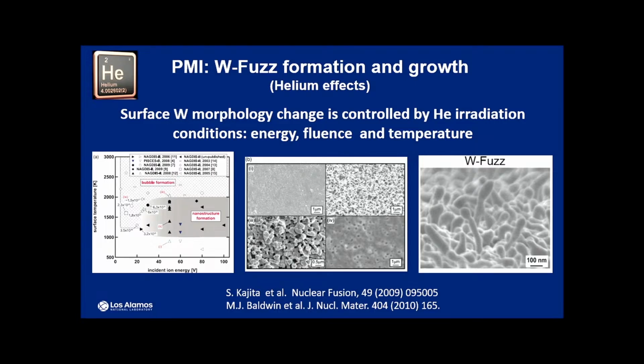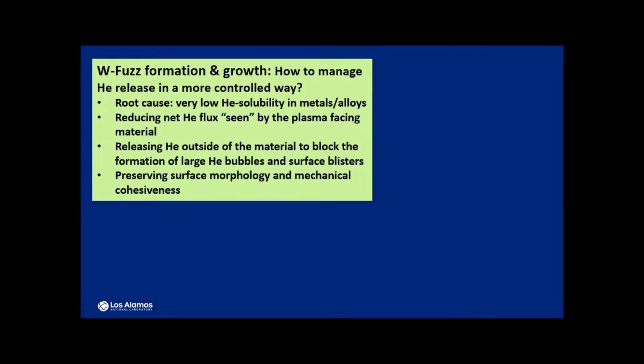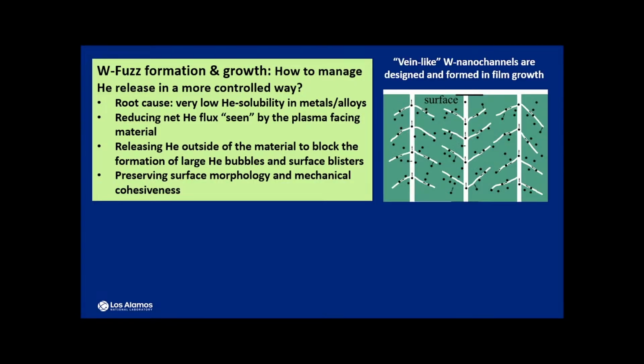This is not unique to tungsten. It happens to many metals. The root cause is that many materials, including metals and alloys, have no solubility for helium. Helium just does not form a solid solution with them. We cannot change the plasma part of the spectrum, so we thought we needed to do some different materials science to accommodate this helium flux effect. The idea is that we purposely produce some microstructure in the material which has pathways for the helium to release when it is being irradiated or implanted. So the net flux seen by the surface of this material is going to be reduced. Hopefully that is going to reduce the fuzz formation.